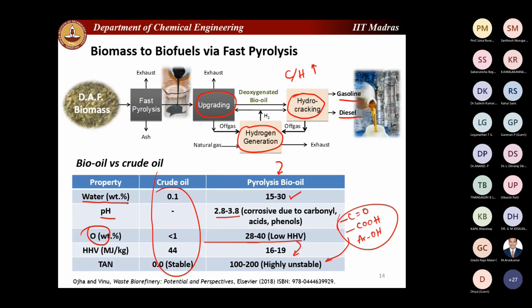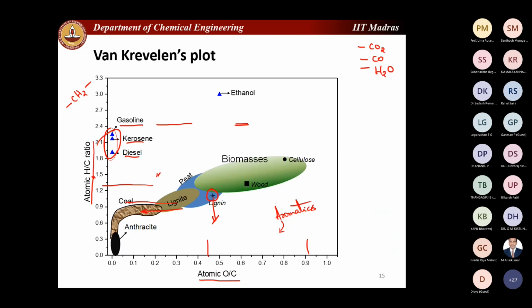Okay, and when it comes to the quality of this bio oil with respect to the crude oil, we can certainly say that the bio oil has a significant amount of moisture in it as compared to crude oil, because of the lot of the dehydration reactions that occur in the biomass, and because it contains a lot of these oxygenated organic compounds, so it presents a very low pH value. That means it is highly acidic, and so its acid number is high, right? And because of very high amount of oxygen that is present in it, it presents a very low calorific value. And so this essentially means that you need to do a lot of upgradation of